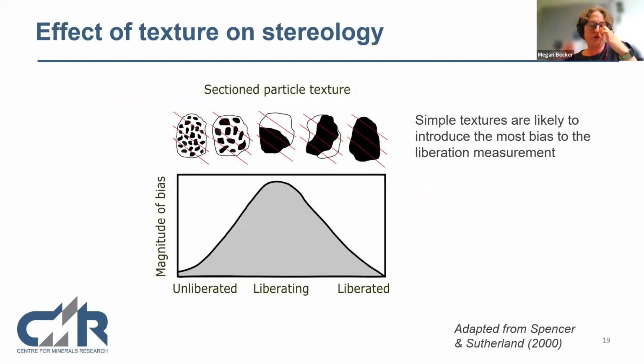And then the other thing to remember is that it's the simple textures that have the worst bias. So with this texture here of a simple binary, the magnitude of the bias is the most. Whereas with this texture here with the black, for any intersection, so we look at where the red line's going, I'm pretty much still going to get the same answer. And if it's fully liberated, whatever the red intersection through the particles, I still get the same answer. It's these simple textures that introduce the most bias.